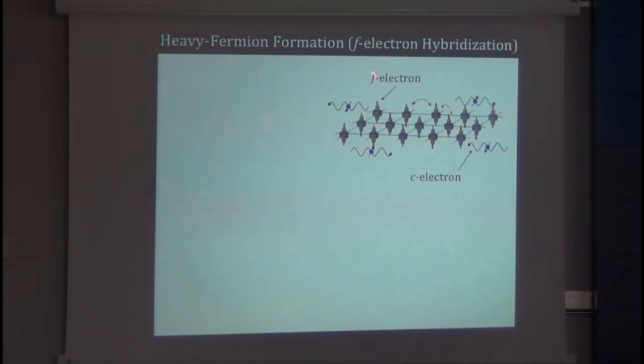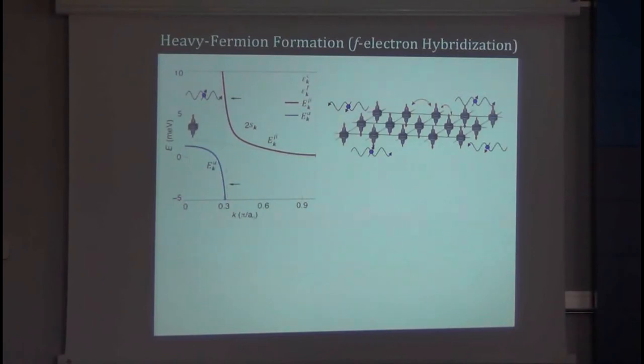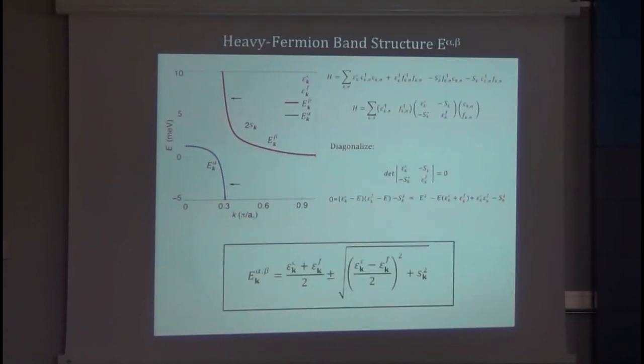Now, what we're going to talk about is hybridization of these electrons with those electrons. And here's what happens. You have a light band of these delocalized electrons. These localized electrons have an almost flat band, or sometimes it's completely flat. And now if you introduce an interaction between them, you produce an avoided crossing and you get two new heavy bands. For those of you who like quantum mechanics, you can write a Hamiltonian for the c electrons, for the f electrons, and then you write a hybridization term which creates an f electron and destroys a c electron and the Hermitian conjugate. Then you can write this Hamiltonian in matrix form, like this.